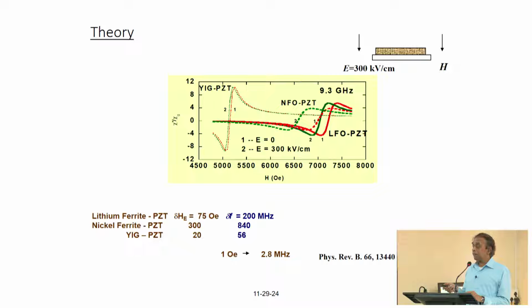So, the tuning in this case is small, but it is good enough if there is a device operating at room temperature and you want to make it operate over a wide change in temperature, maybe from 0 to 60 degrees. Then the tuning that you can do with the voltage is enough to compensate for any shift in the temperature of the device. So, it is a very limited capability, and we cannot tune the device over several operating bands. That is not going to be possible.